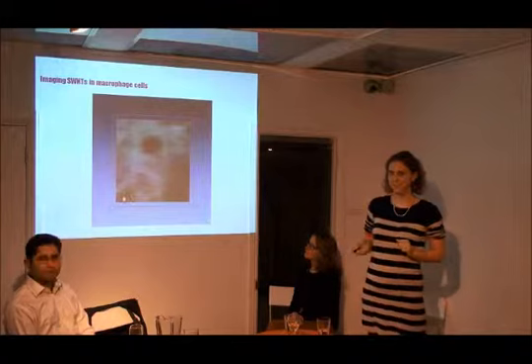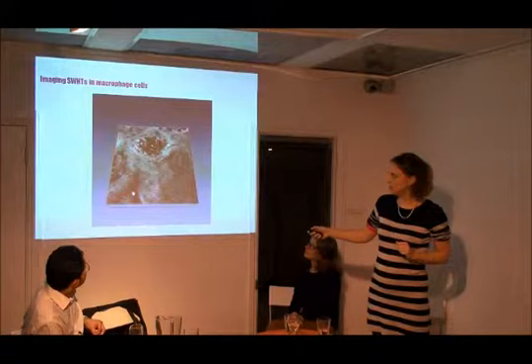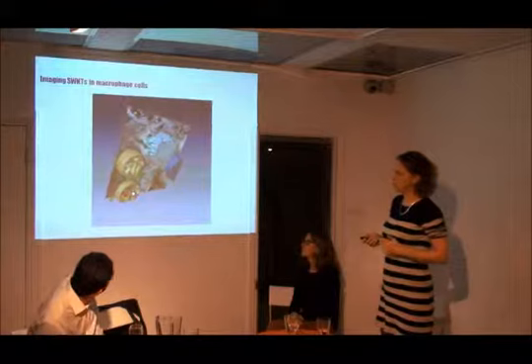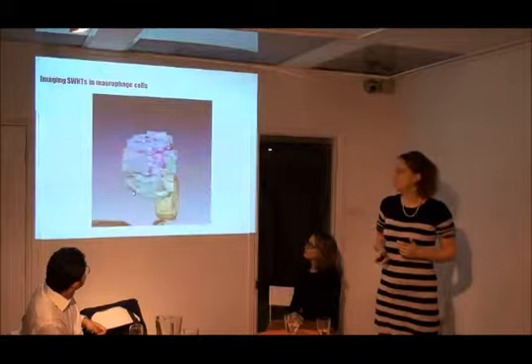So here's a 3D volume reconstruction, here's my cell, and here are my nanotubes. They're just bundled within kind of a vesicle inside the cell. So they're not spearing, they just bundle together because these are very flexible structures. And then what we've done is just to threshold the different intensity levels, and here's this vesicle structure, and here are the purple, my bundles of single nanotubes in the cell. Okay. So these are non-toxic to the cells.